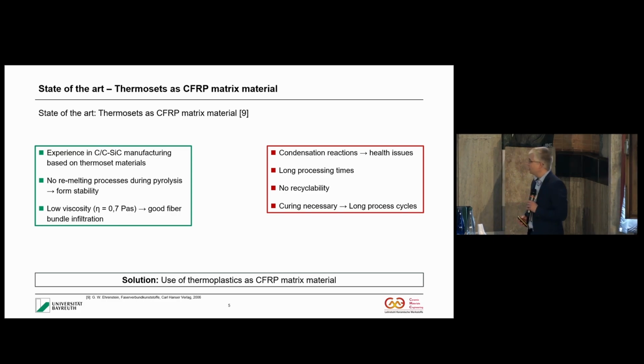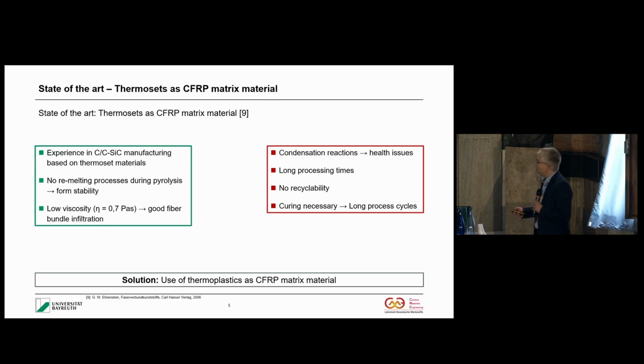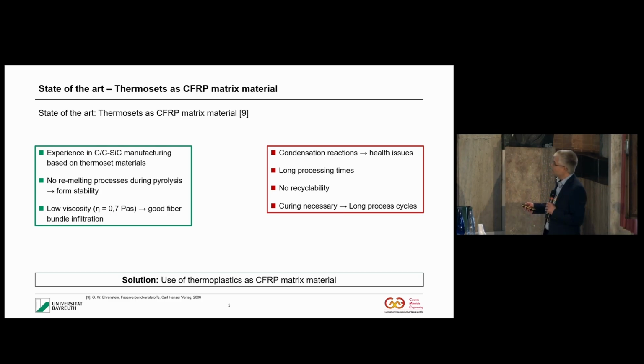So currently, as many of you know, we use thermoset polymers, which have their advantages. First of all, they are available, we understand them, they have been tested for a long time. They also have the advantage that they are not remelting during pyrolysis, so they have a good stability. They also have a low viscosity, so that means we have a good fiber bundle infiltration. However, one big disadvantage is that they have a condensation reaction. So the condensation reaction induces porosity, for example, and porosity then impairs your mechanical properties.